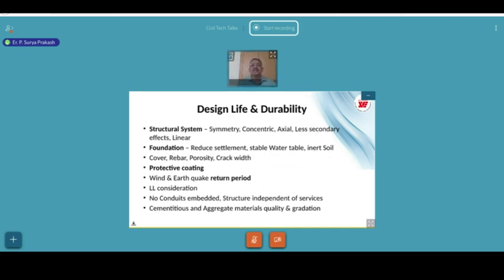So the structural system, finally, the design life and durability to be ensured, we must have symmetry in the structural system, concentric loads as much as possible, reduce the eccentricities, axial, predominantly axial force transfer, and less secondary effects, that means the non-linear effects, and linear within elastic range. The stresses you try to maintain within the linear range, and in foundations reduce the allowable settlements and stable water table to be maintained. How we can do? You can do the sheet piles and all, and inert soil. Try to make the soil inert, that is exposed to the structure, and cover, rebar, porosity of the concrete and crack width in the design. Try to minimize the crack width in the design. If you have to, design for flexure and stability.